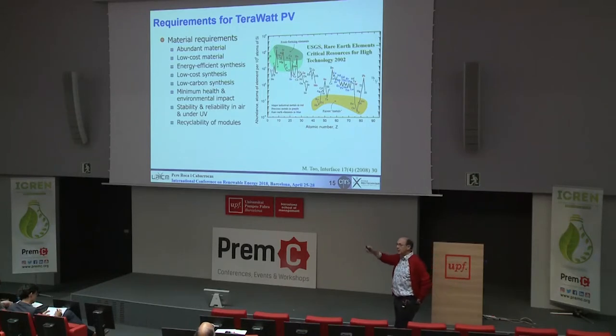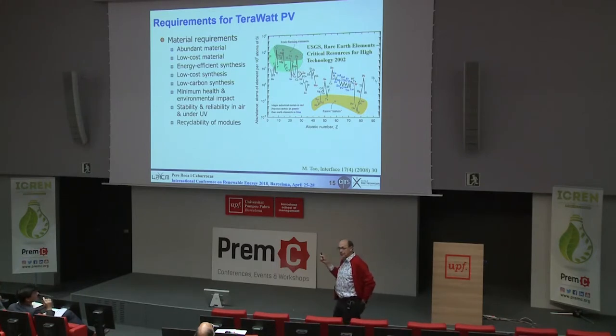And then when you have this chart of PV technologies, in fact, crystalline silicon is one of the most abundant materials, so that's okay for silicon. We have an abundant material. That would not be the case for cadmium telluride, tellurium here, or for CIGS with indium, which is low. So we have abundant material, but we have a process which is not very energy efficient.